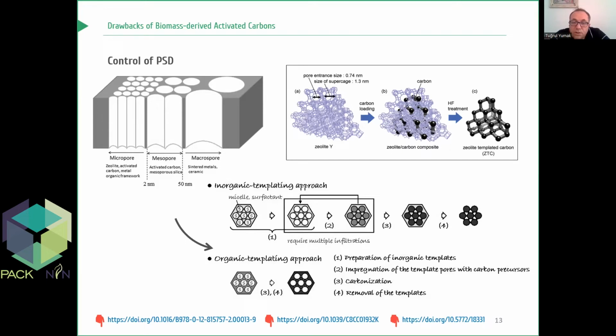Unlike the well-known ordered mesoporous carbons obtained by using mesoporous silica templates. Perfect results we have, but again, we need lots of mesopores to ensure the mobility of electrolyte ions to the micropores. So it is clear that we need much more effort to synthesize new templates with micropores and mesopores together in the same structure.